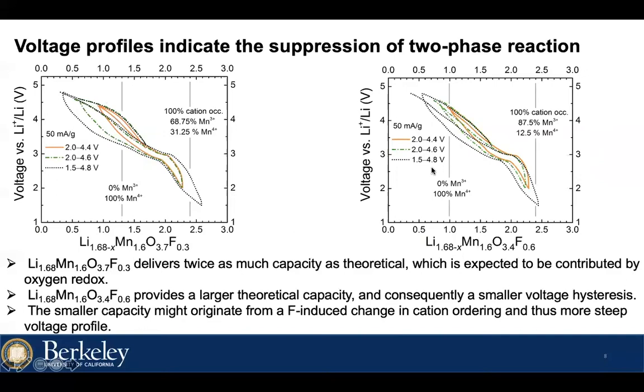The compound with higher fluorination level provides more theoretical capacity. So the hysteresis is also smaller because of less oxygen redox contribution. But it delivers less capacity, which might be caused by the fluorine-induced short-range order, which makes the voltage profile more steep. And for both of them, there is no voltage plateau at the 3 volts region, which is observed in older spinel. As we proposed, this is because of the cation disorder induced by the lithium over-stoichiometry.